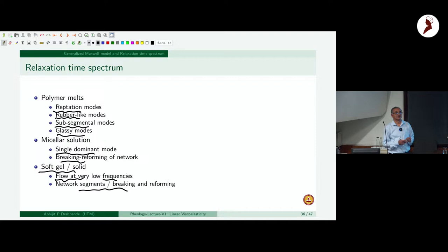or it is a supramolecular polymer system, in which case the supramolecular polymer can be assembled in two ways. One is small molecular gelators assembling into fibrils and then a gel, or you could have polymers with sticky groups, so that you have temporary or semi-permanent crosslinks. In each of these cases, unlike in a melt, no such reptation is possible. So reptation is not present here, because microgel particles do not have any of that feature. And polymers and supramolecular materials again do not have reptation possible.